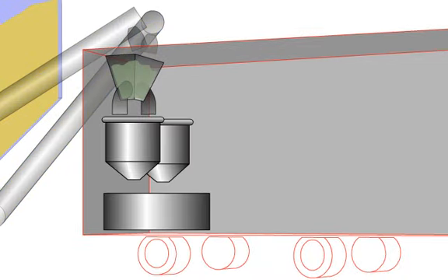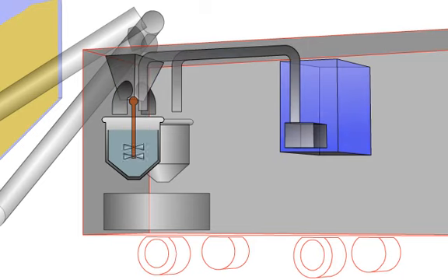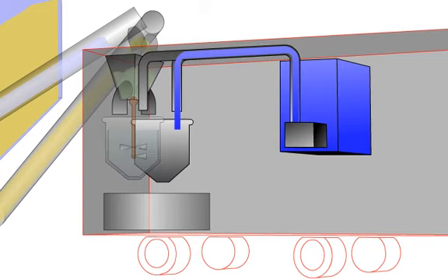The slurry blending consists of two mixing tanks, which each have integral load cells that individually weigh each component as it's introduced into the mixer. With a 1.5% tolerance per batch, the dry materials and water are thoroughly mixed together by high-speed impellers. As one mixer has begun the slurry mixing cycle, the other mixer is receiving. Thus, a continuous amount of slurry is produced.